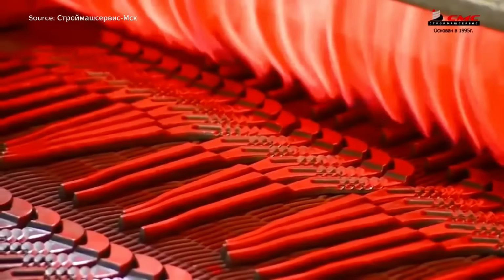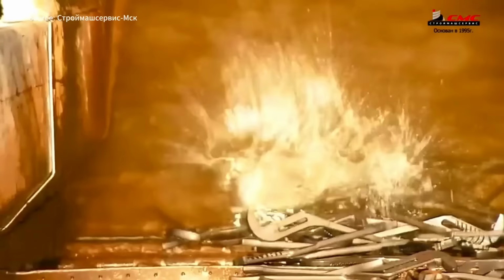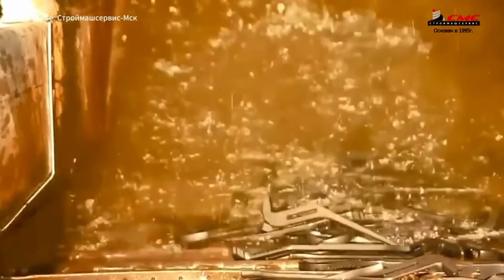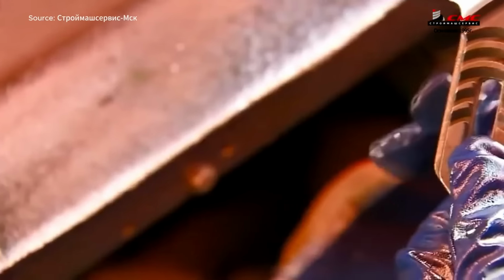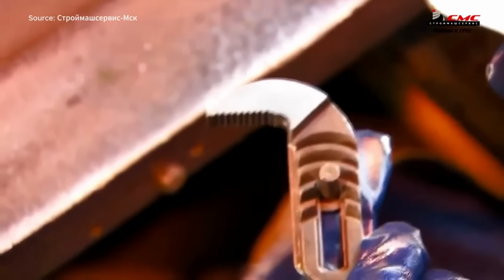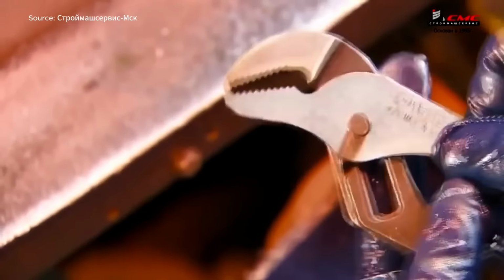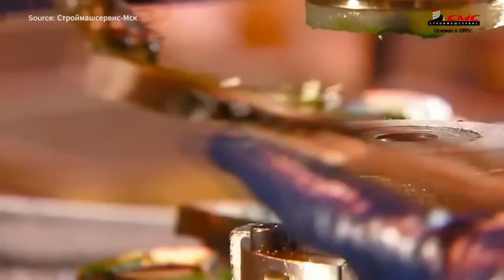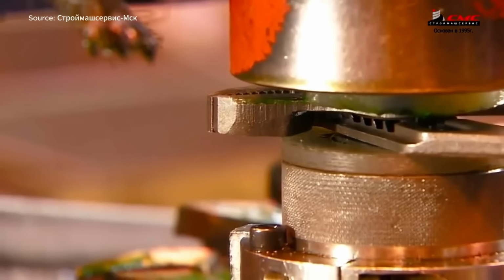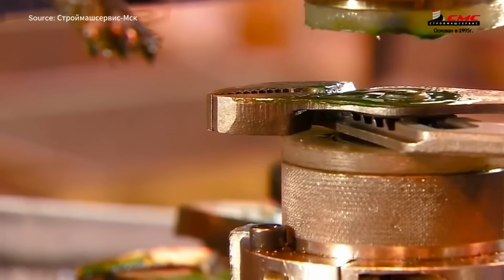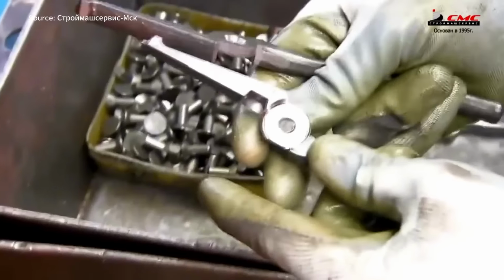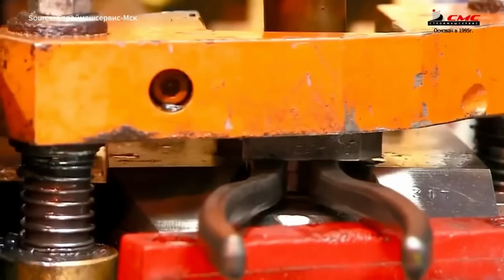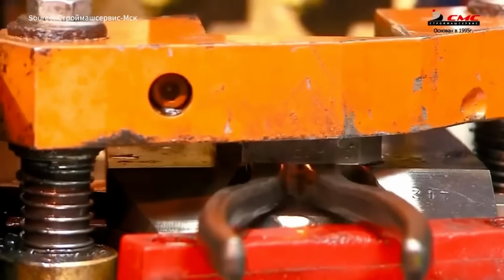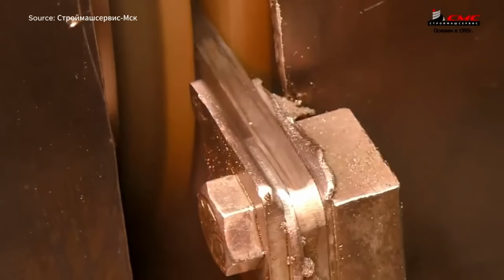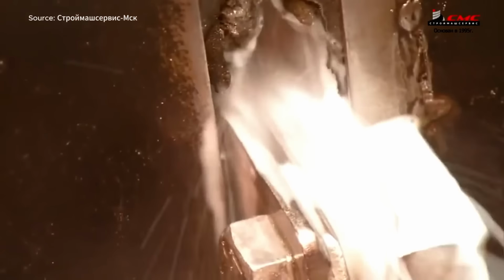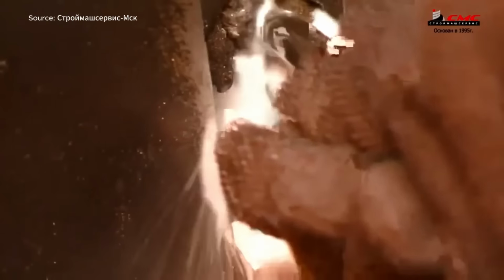Heat treatment is next. Halves are baked at over 800 degrees Celsius for 2 hours, then rapidly cooled in a salt bath for maximum hardness. Some jaws are even laser hardened for extra durability. The halves are then assembled using a steel pin, secured by high-speed friction or press fitting, depending on the type. Edges are ground perfectly flat with abrasive wheels, and another round of heat treatment in oil ensures lasting strength.